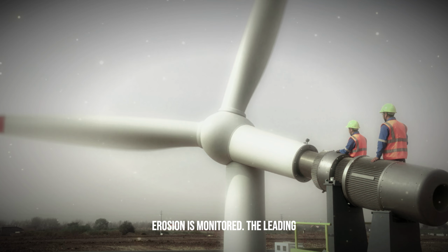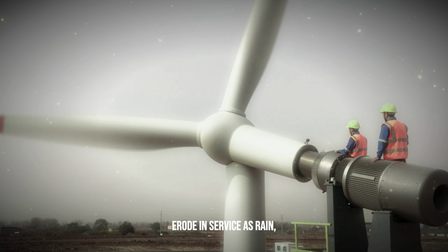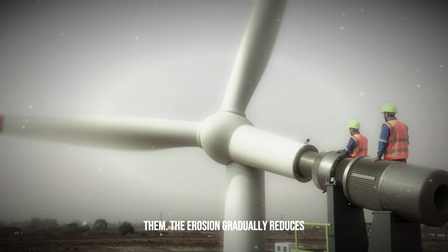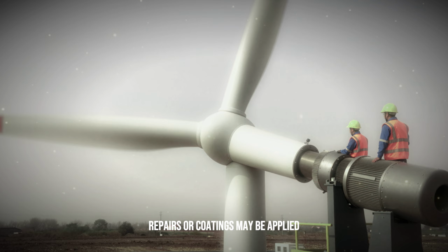Blade surface erosion is monitored. The leading edges of the blades gradually erode in service as rain, dust, and ice particles impact them. The erosion gradually reduces the aerodynamic efficiency of the blades. If erosion becomes severe, blade repairs or coatings may be applied to restore efficiency.